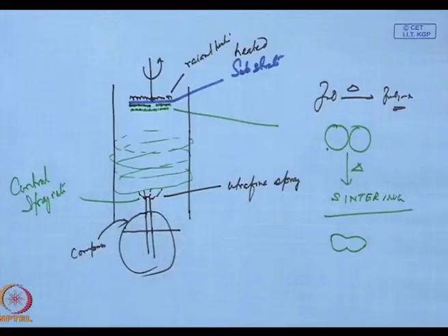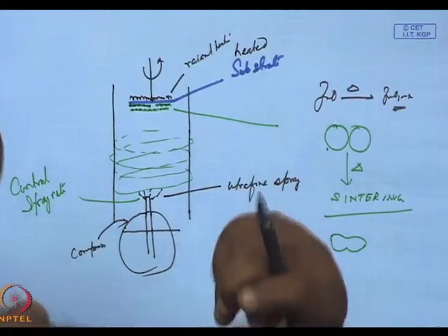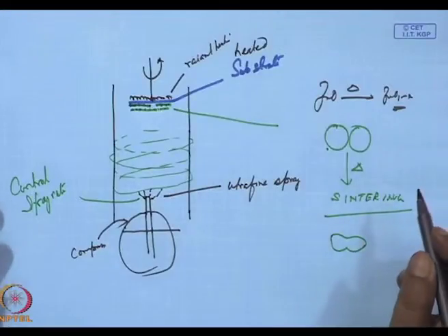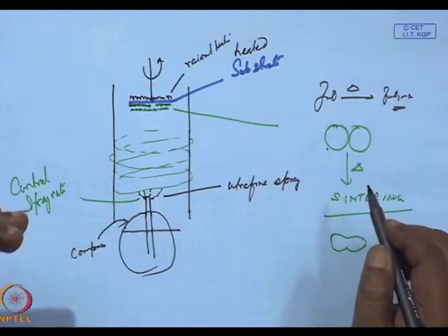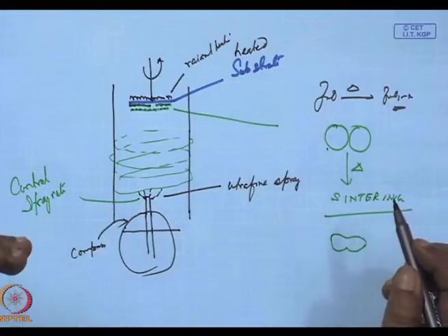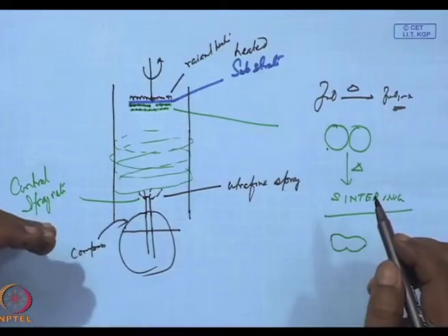Because if the spray rate is too high, even if the substrate is heated, too much material will fall on the substrate and start evaporating, causing lowering of temperature. As a result, we will not get the dense sintered film.